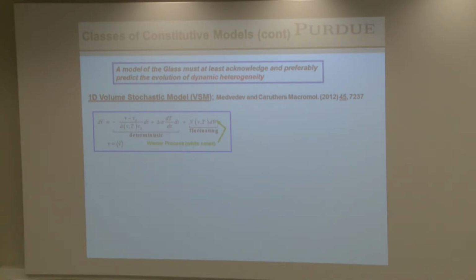Look at the first term here. What it says, divide through these first terms by dt. So this would say the rate of change of volume is equal to the change in temperature with time times the coefficient of thermal expansion. So that's just normal temperature changes, the material thermally expands, and it is all slave to the rate of change of temperature. This one here is the relaxation part, and it says how fast does the material relax?